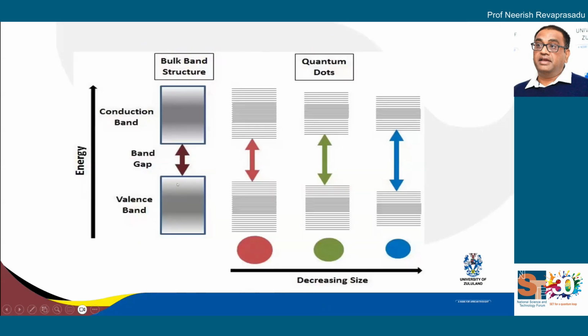You can see in a normal material, the bulk material, you have a band gap. But when you have a quantum dot, or a material that's very small, between 0 to 5 or 0 to 10 nanometers, you have an increase in the band gap. And you can see as you change the band gap, you have a change in size, and a change in color. So the emission that's given off is directly related to the decrease in the size and increase in the band gap. So these are the fascinating properties of quantum dots.